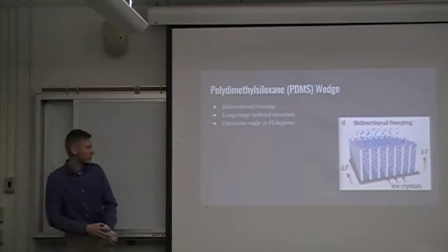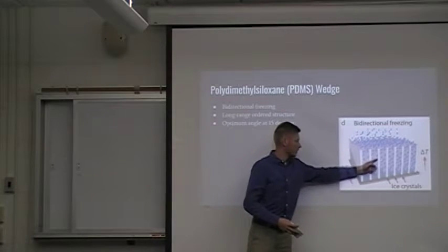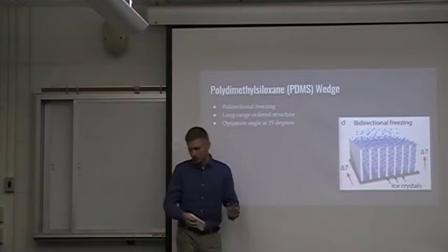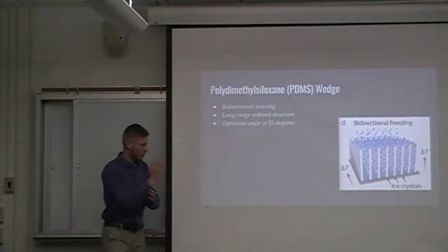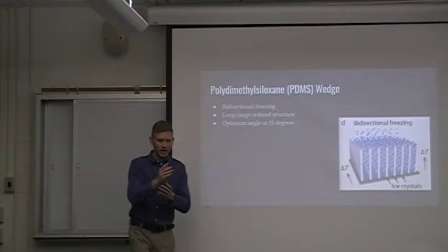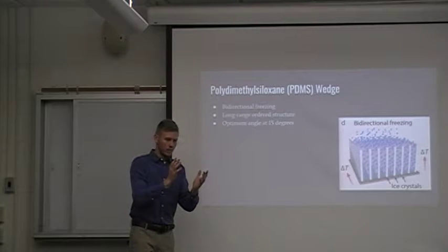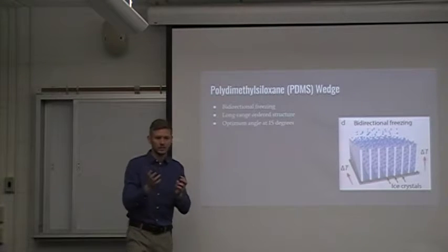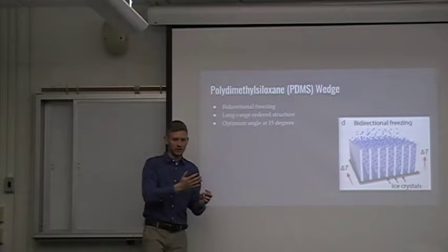Alright, so the ice crystals are indicated by the white and the temperature gradient. So the ice crystals are growing up through the lamellae. The ice crystals separate the lamellae, and then as they grow, the bridges are deposits of excess graphene that cannot be added to the lamellae.